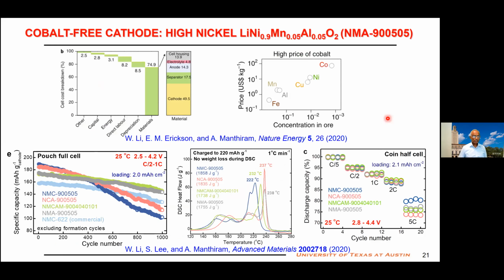Now, I talked about cobalt. So I compare 4 materials here. All of them have the same nickel content, but some of them have cobalt. Whenever you see C here, that means it has cobalt. NMA does not have any cobalt. That is this curve. You see here, the capacity retention is as good as or better than some of the cobalt-containing materials. We are not compromising thermal stability. We are not compromising rate capability.